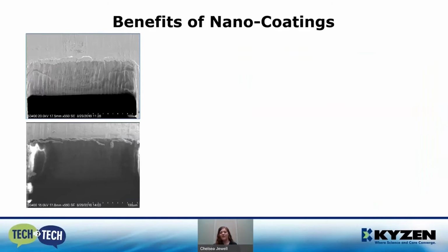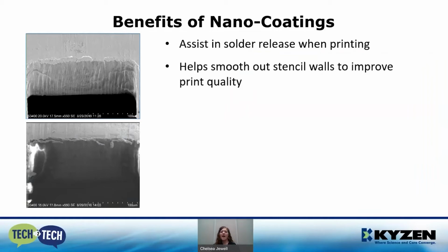So let's get into the benefits of nanocoating. Nanocoatings will assist with solder release when printing. As you can see in our images, the top image is a stencil aperture that's been laser cut, and the surface is very rough, and that promotes a lot of adhesion of the solder paste to the wall of the stencil. Whereas in our second image, a nanocoating has been applied and it's helped smooth out that surface. So it helps with solder release, and that will improve your print quality.